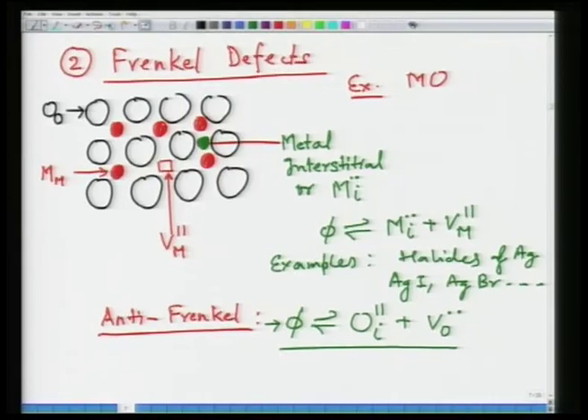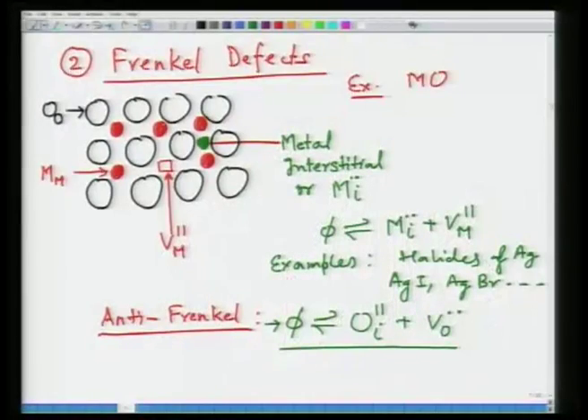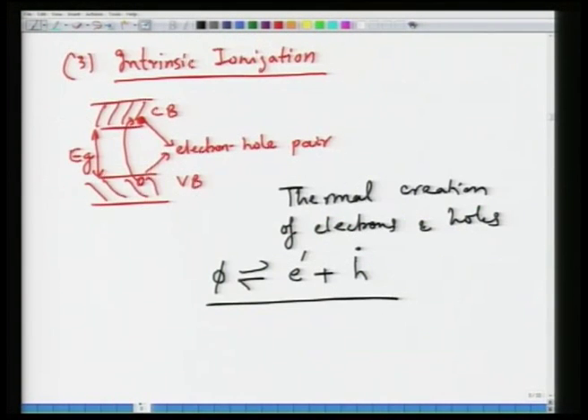Another kind of important defect is the Frenkel defect. Frenkel defect is formation of a metal interstitial coupled with formation of a complementary metal vacancy, or in case of anti-Frenkel, it is formation of an oxygen interstitial complemented by an oxygen vacancy. So, these are the two most common defects that occur in stoichiometric solids. And third is intrinsic ionization, which is nothing but excitation of electrons from the valence band to the conduction band, giving rise to an electron-hole pair, and this can occur in any material.